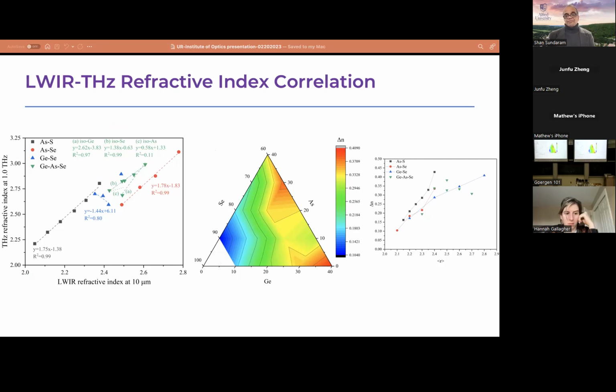This is one of our goals: can we recognize what other optical functions these glasses can potentially be used for? Chalcogenides have so far been used commercially mainly for long wave IR applications. But now this may give you some ideas. Some of the chalcogenide glasses potentially can also be used for terahertz signature identification, integrated photonics, possibly. All of this is possible. So once again, we have also measured the delta n in the system as a function of composition, and we are plotting average coordination number of various structural units. So that clearly shows that we can indeed vary various glass mixtures. We are getting structural mixtures in these glasses, and we can basically tailor a whole range of terahertz properties and also other properties like long wave IR refractive index.